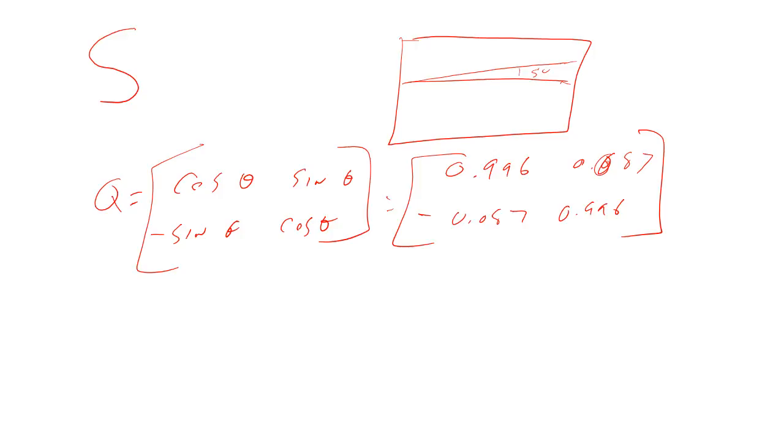So what's the formulaic way to compute the Young's modulus? And here's where I think everyone went completely off the rails. In the form that it's given, I give S as a 6x6 matrix. Because it's basically a 2D problem, you can reduce this down.